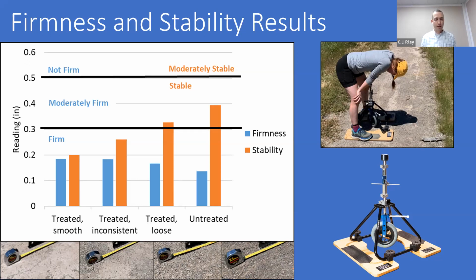So you can see here that at the 0.3 inch level, and the blue bars, that's the firmness measure. And so really all of these areas were considered firm. We didn't have any in the moderately or not firm areas. As far as stability goes, it stands to reason that the untreated surface was less stable, that as you might rotate a wheel on that surface, that you would move more material and that wheel would drop farther into the surface. And so you can see that.